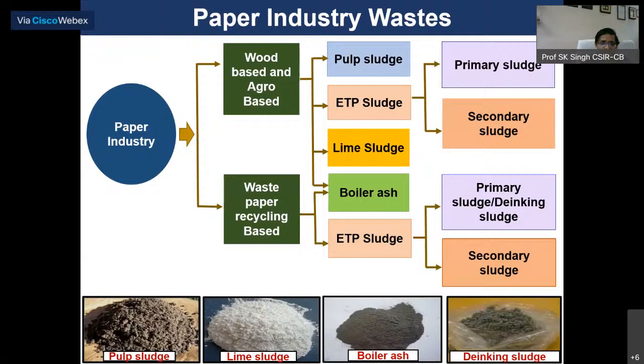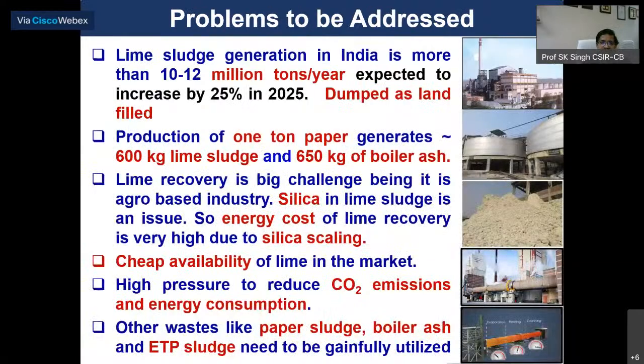One is wood-based agro industries and waste paper industry. So we have mainly pulp sludge, ETP sludge, lime sludge, boiler ash, and different combinations with different characteristics. So we have to look into that. As I have told, from the data we have correlated that about 1 ton of paper usually generates about 600 kg of lime sludge and 650 kg of boiler ash and coal ash.